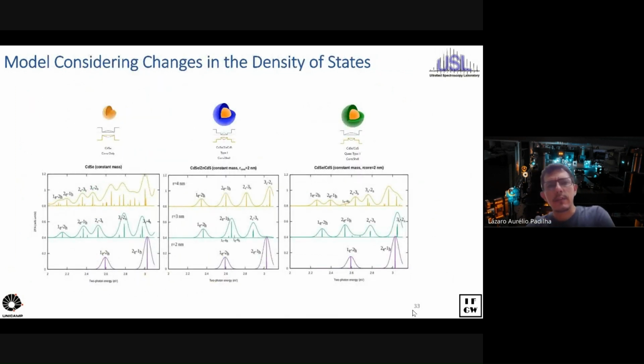So to rationalize what we have seen, if you look at the core-only quantum dots, they have a change in the density of states much more pronounced than you would have, for example, for core-shell type 1, where when you make the total volume increase from 2 to 4 nanometer, it changes just a little bit, while this changes quite a lot, increasing drastically the density of states and making a steeper volume dependence for core-only than for core-shell.